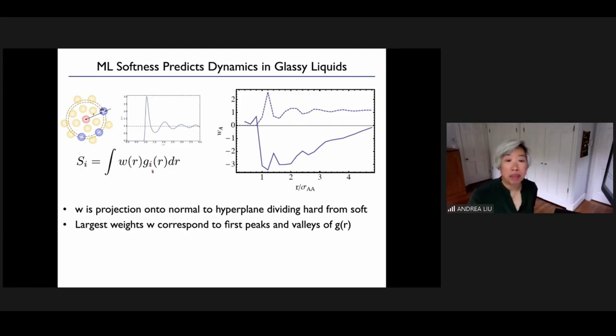What we found is that particles that are much more likely to rearrange end up having lower first peaks of their pair correlation function and higher valleys, and so the weights are concentrated at the peaks and valleys of the pair correlation function. All right, so softness really, and this was for glassy liquids, ended up giving you a measure of the strength of the cage in which each particle is trapped.